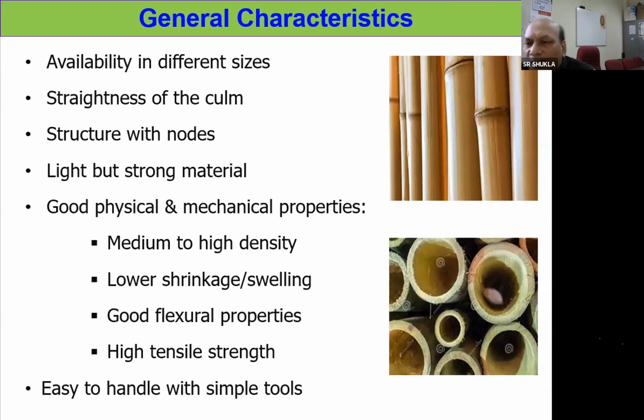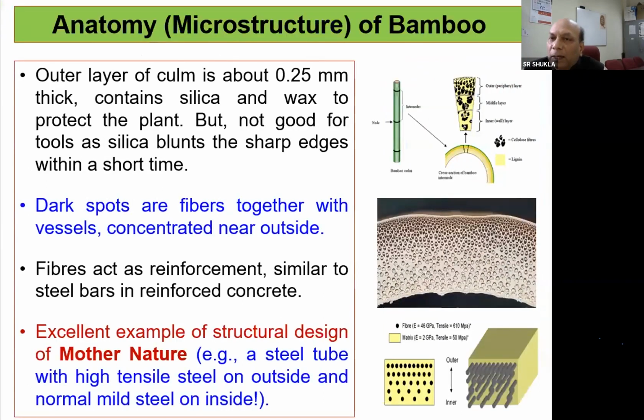Bamboo has good physical and mechanical properties, like medium to high density. The bamboo density varies from maybe 0.5, 0.6 to 0.9 or 1 gram per cubic centimeter. This is the range across different bamboo species. It has lower shrinkage and swelling in the culm, in wall thickness and lengthwise. It has good flexural properties, so the bending strength of bamboo is quite good. And as I said, it has high tensile strength and is very easy to handle with simple tools.